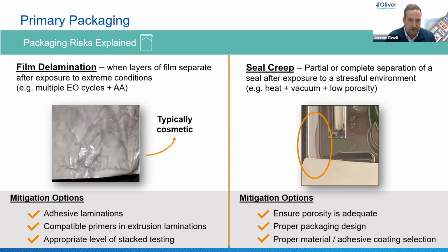And then another risk is seal creep. Seal creep can be defined as partial or complete separation of a seal after exposure to a stressful environment. So again, within sterilization, many types of sterilization, you have a combination of sometimes heat and vacuum. And when you combine that with low porosity or blocking porosity, you could have a difficult time getting the air in and out, and it could put stress on your seals. So some mitigation options are ensuring porosity is adequate. So using Tyvek, even medical papers, just ensuring that that is adequate in the design, but also the packaging design, the system design, and protective packaging, making sure you're not blocking that porosity is essential as well. And also proper material and adhesive coating selection comes into play. And we'll talk a little bit more about that on the next slide as well.